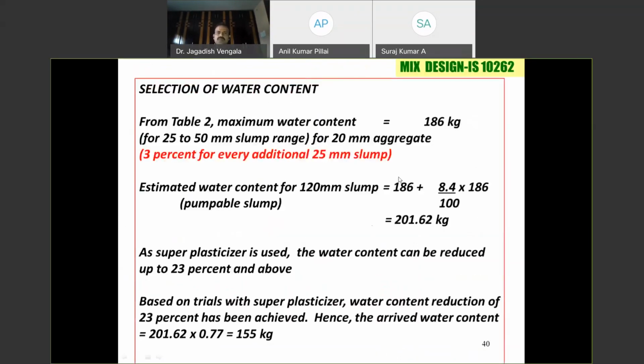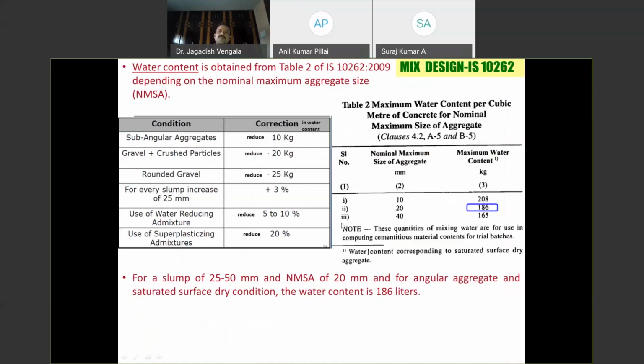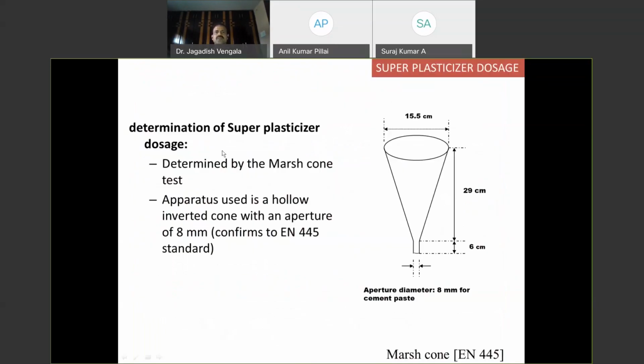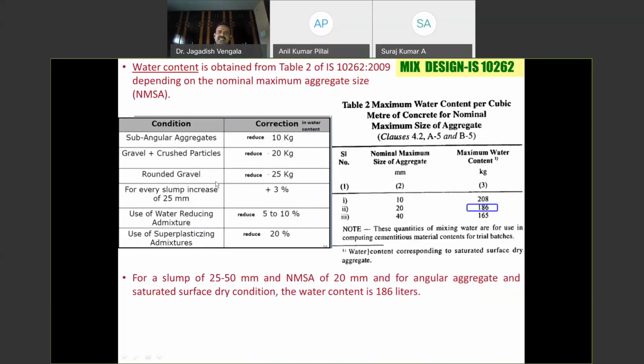Coming back, once you add the required superplasticizer dosage based on the trials, a water content reduction of 23% was achieved. So the rest is 77%, and the water is 155 kg or liters. Suppose you have different kinds of aggregates: if you have rounded coarse aggregates, you have to reduce the water content by 25 kg, and if it is subangular aggregate, you have to reduce it by 10 kg. So you have to adopt this depending upon the material property. Many times, once the source of material changes, people follow the same mix design given from the lab. You have to make corrections, fine tune the mix design, conduct a small trial at the site, and then go ahead.